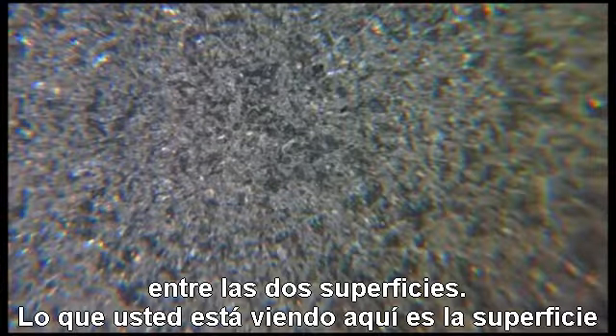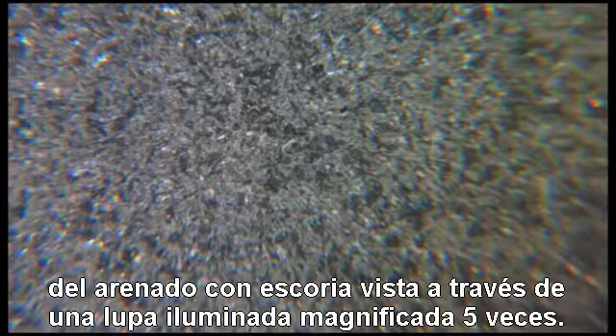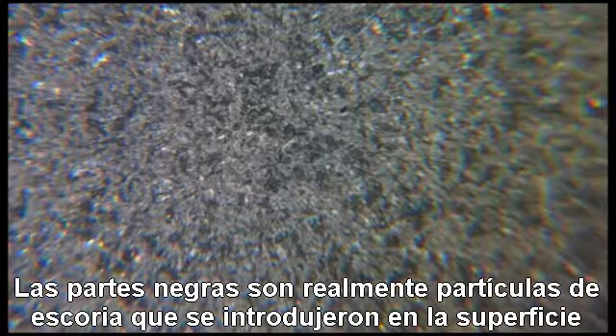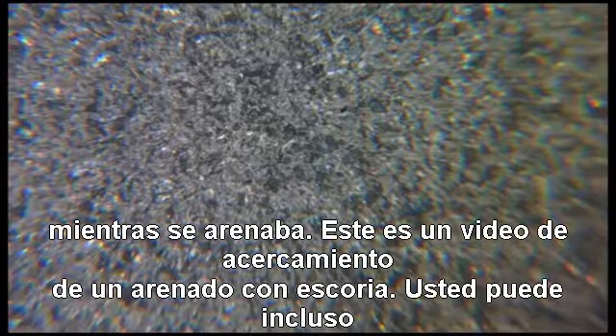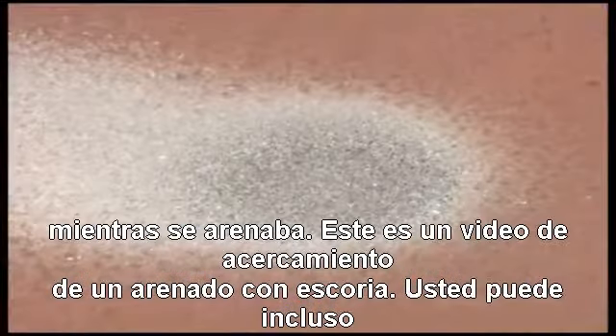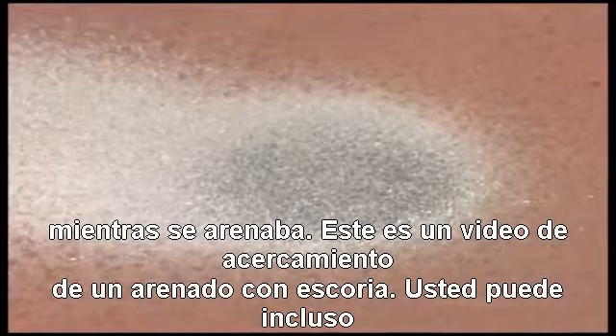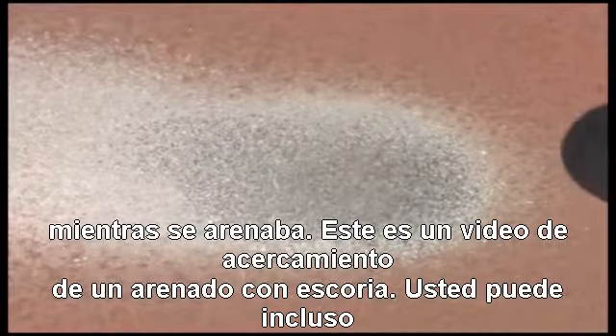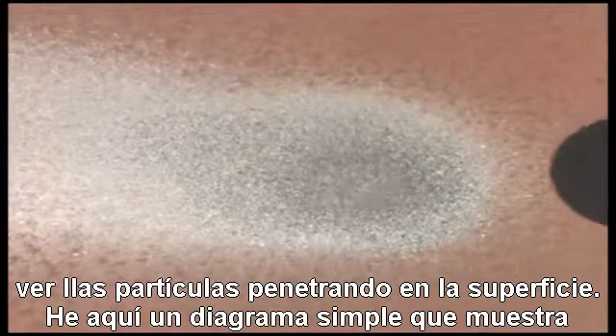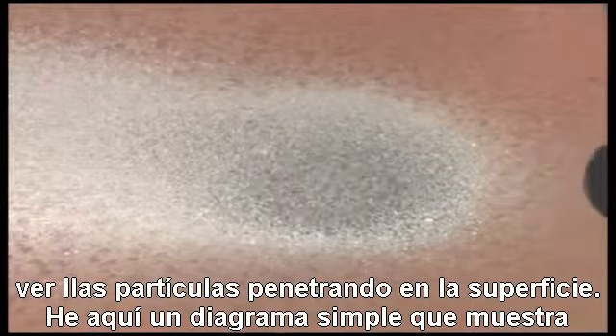Now let's look at what is causing the difference in color between the two surfaces. What you are seeing here is the surface of the slag blasted plate looking through an illuminated surface 5 times magnifier. The black particles are actually slag particles which have embedded on the surface while blasting. This is a close-up video of a blast nozzle blasting with slag. You can actually see the black slag particles penetrating onto the surface.